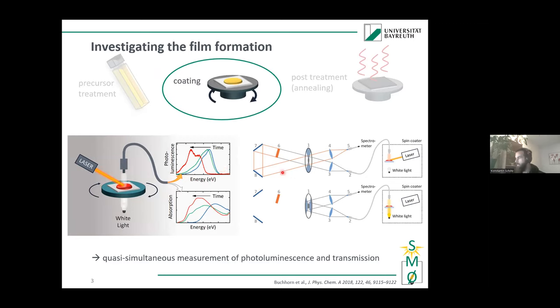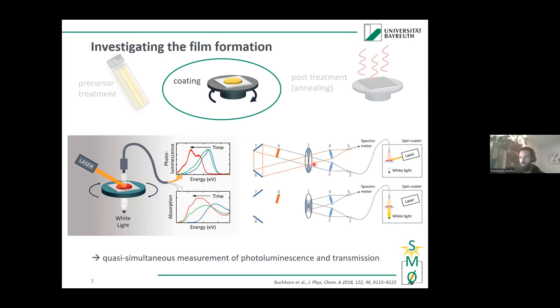We record frame by frame. For a PL frame, the white light is off, the laser is on, and emitted light from the sample is collected by an optical fiber into a detection system. A chopper wheel directs light through a filter that removes the laser wavelength, then to a spectrograph. For absorption measurement, the laser is off, the white light is on, and the chopper wheel reflects the white light directly to the spectrometer.